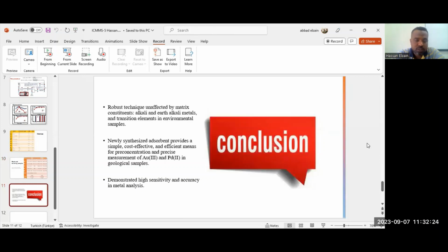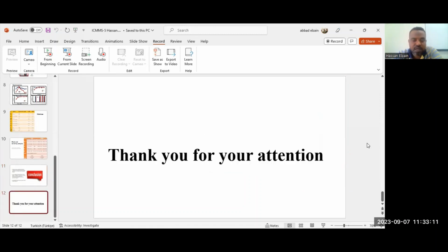In conclusion, our proposed technique is unaffected by matrix constituents like alkali and alkaline earth metals and transition elements in environmental samples. The newly synthesized adsorbent provides a simple, cost-effective, and efficient means for pre-concentration and precise measurement of gold and palladium in geological samples. It demonstrated high sensitivity and accuracy in metal analysis. Thank you very much for your attention.